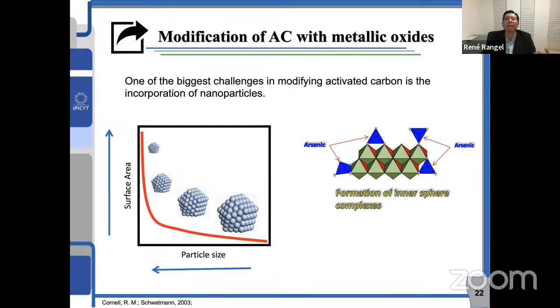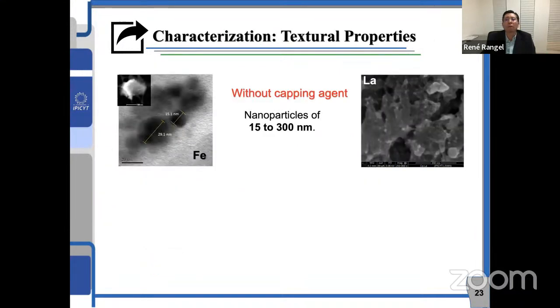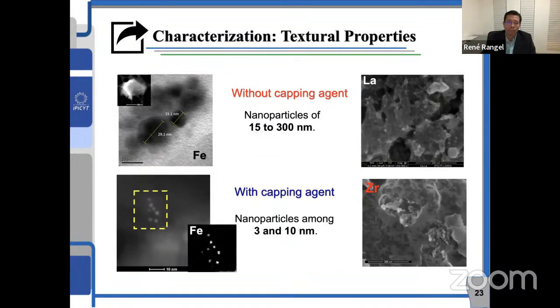One of the problems is, if I have very small particles, how can I remove these particles? These particles cannot go in the water. We cannot drink them, otherwise the problem will be worse. So what we have done is anchor this kind of particles on activated carbons. In this case, we managed to anchor iron oxide and lanthanum particles on activated carbon, ranging from 15 to 300 nanometers. But if we use a capping agent, as I will explain in the next slide, we managed to reduce the particle size of these metal oxides quite a lot, to 3 to 10 nanometers. And the dispersion of these particles on the carbon surface is very homogeneous.